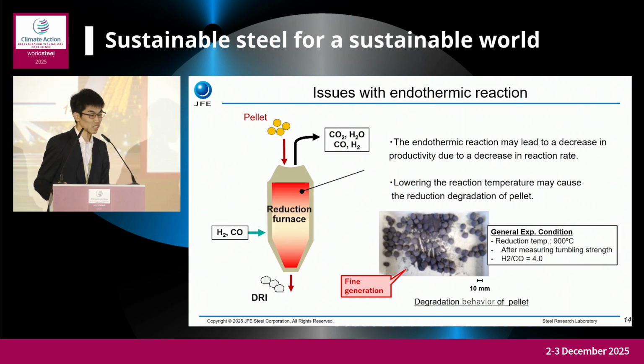In this photograph, the reduction was carried out under the condition of hydrogen to carbon monoxide ratio of 4. And the tumbling test was performed on the sample after the reaction. As you can see, the strength of the reduced sample decreased and fine powder is generated. It is expected that the use of low-grade pellets will increase in the future. We think that low-grade pellets are likely to suffer reduction degradation. If in this process the hydrogen ratio in the reducing gas does not increase, it is thought that it is possible to minimize the occurrence of reduction degradation.